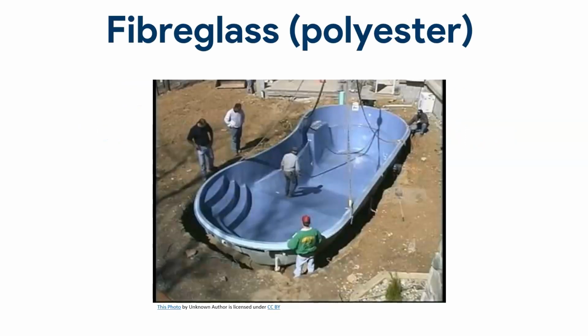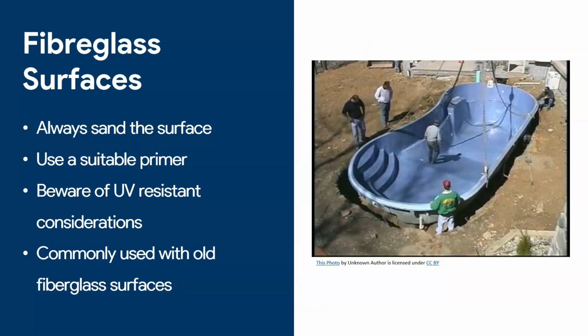Let's look at fiberglass now. This is an interesting one because I get this a lot with pool coatings. People have old fiberglass pools, they're worn out, and they want to just recoat their pools. And actually, you can do that with epoxy. You can recoat old fiberglass pools or fiberglass surfaces with epoxy. However, you should always sand the surface just to be sure that you're going to get good penetration and nice pores in the surface. You also want to be using a suitable epoxy primer to make sure it just goes into the surface. You don't want to mess about with these things.